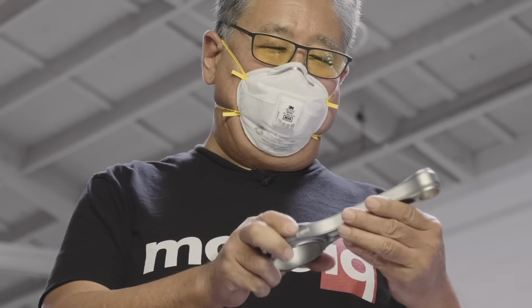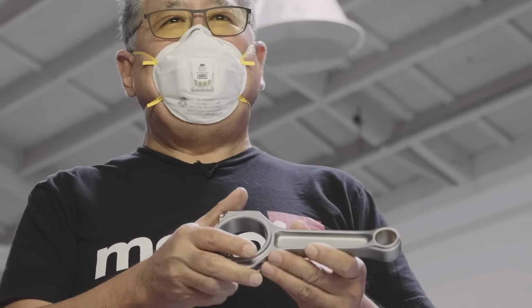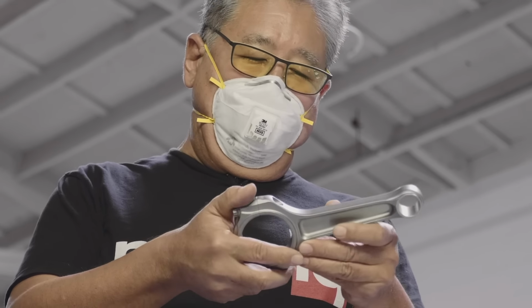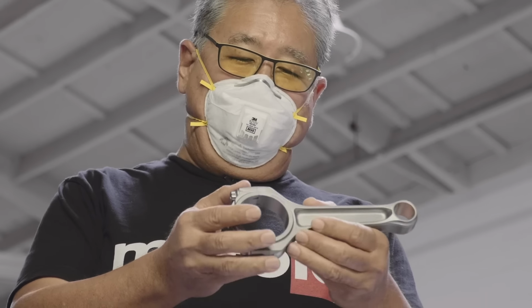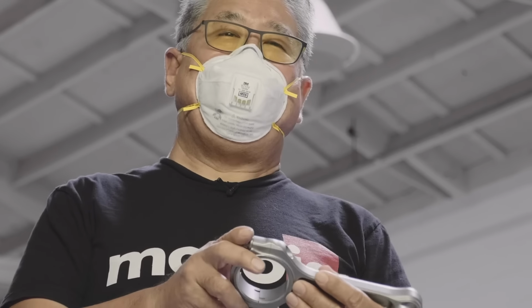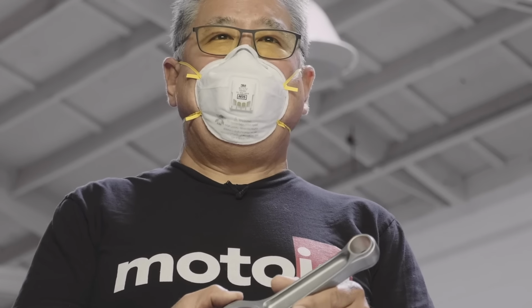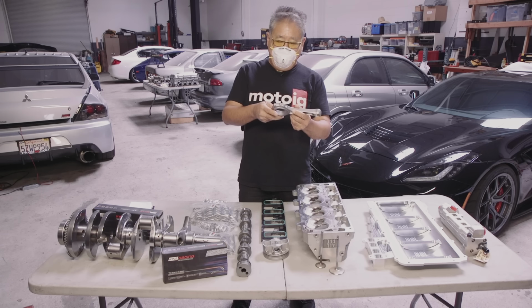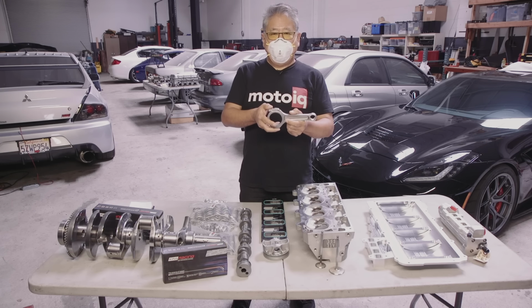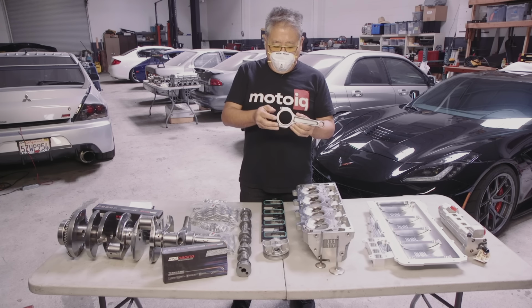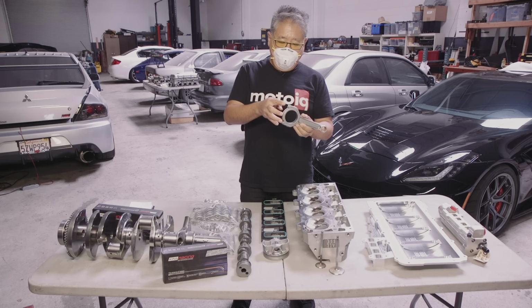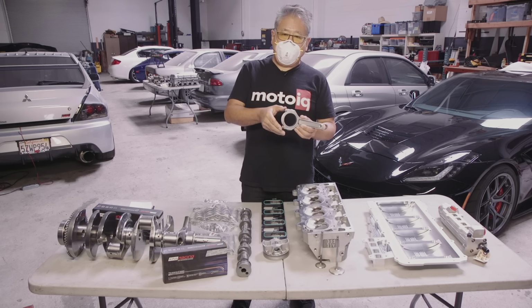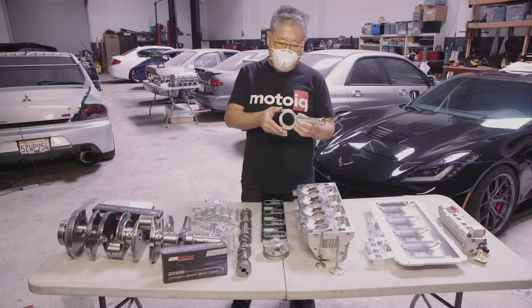The rod is shot peened after it's finished. That helps improve the fatigue strength. It's a really nice piece, and it's actually beautiful to look at. On top of everything that Callies does, we actually WPC the rod, and we cryo-treat it also. So the rod's cryogenically treated. The rod bolts are removed, and they're WPC treated and cryo-treated. Rod bolts are critical, so we don't want any place where a fatigue crack could start.